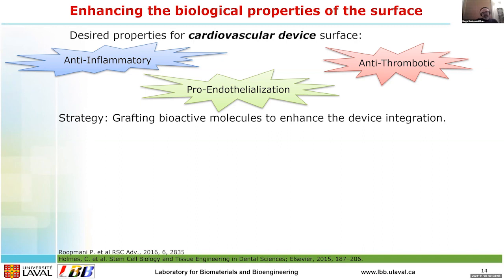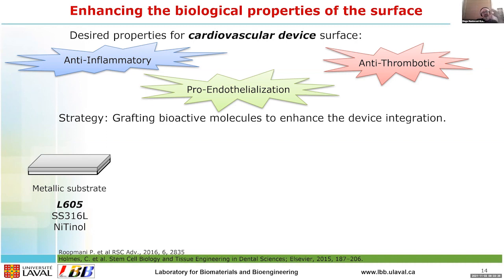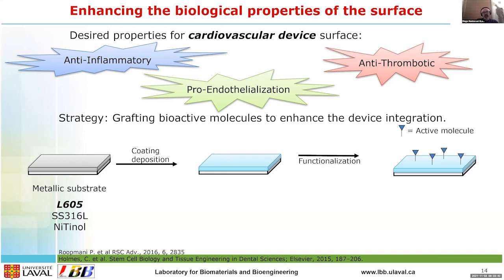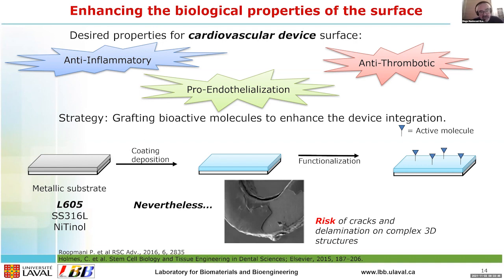So the strategy is grafting ultra-specific, very active bioactive molecules. Sirolimus and paclitaxel are not active. They are mainly repulsive molecules. So the idea that I will enter now, the strategy of the project, was that we mainly work on cobalt chromium because it's the main percentage of coronary stents, and work on the metals. Coating deposition: no, this is not us, sorry, this is what was done in the past. There are a number of coating deposition techniques developed in the last 5 to 8, even 10 years, to coat with a thin layer of polymers.